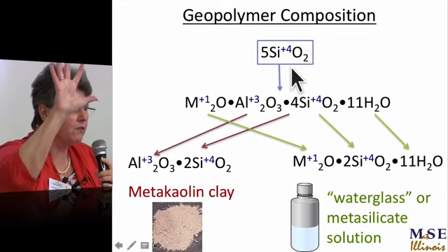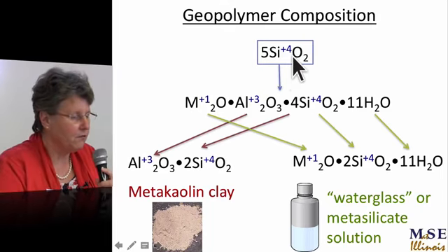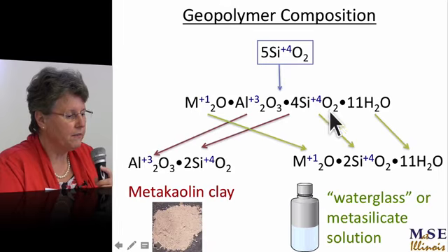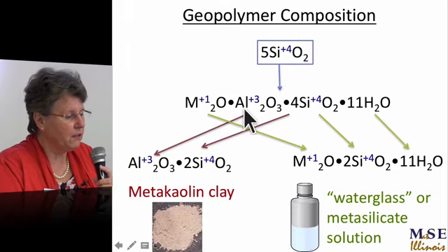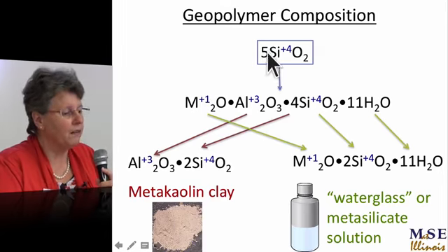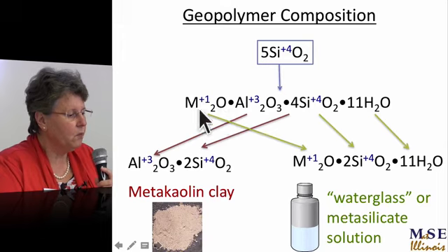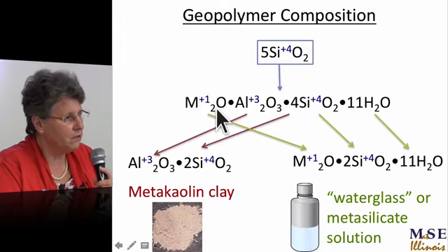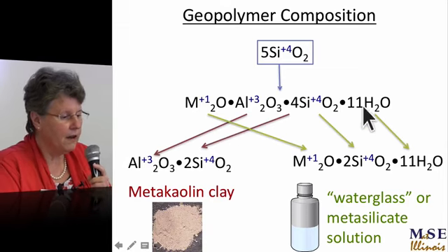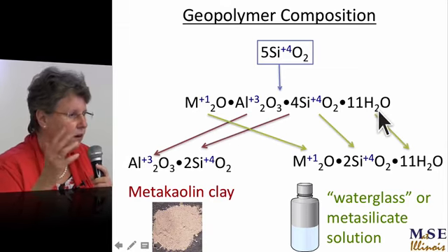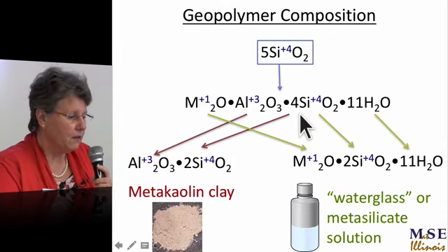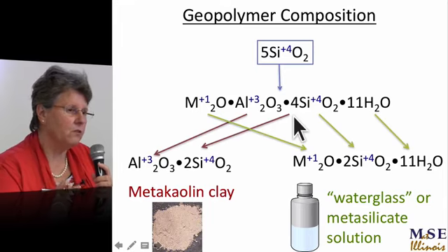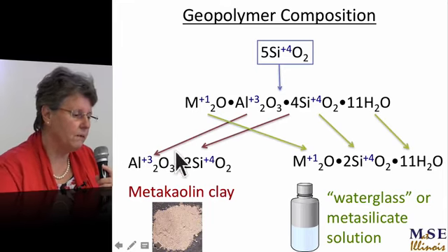So the way I see it, as a physical and inorganic chemist, if you have 5 molecules of silica, the oxidation state's +4. If you take away 1 mole, you get back with 4 moles of silica +4, and you replace that silica with 1 mole of alumina, that's +3. So you need another +1 to make +4 to get back to here. So this is a group 1 oxide: sodium, potassium, lithium, cesium, rubidium, francium, and the water, just for the rheology. You need water. So the way to make it as a material science model system, to keep it simple, is get clay.